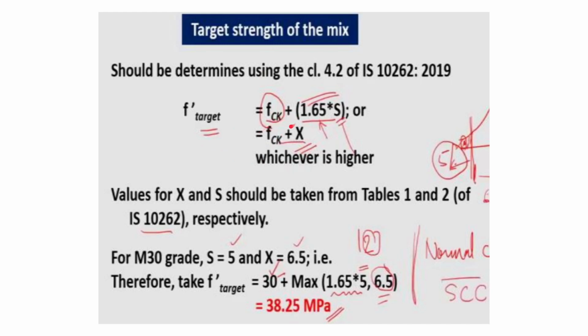it is the characteristic compressive strength plus 1.65 times standard deviation, or characteristic compressive strength plus x, whichever is higher. The x and standard deviation values are obtained from tables 1 and 2 respectively from IS 10262, and for M30 grade the standard deviation s is found to be 5 and x is 6.5. So the f target prime value will be 30 plus max of 1.65 into 5, 6.5, which comes to be about 38.25 megapascal.